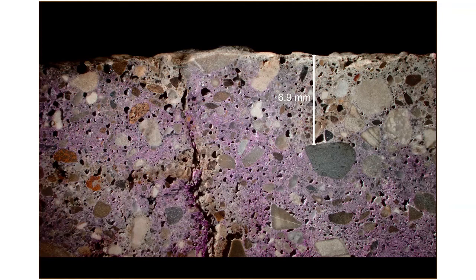Now, another interesting thing to note here, we were talking about air entrainment and the necessity of having little bubbles well spaced throughout concrete to relieve the pressures of freeze thaw and make concrete durable in the severe freeze thaw environments of which we know our bridge decks, curb and gutter, sidewalks, pavements go through. And note all the little kind of black bubbles. We've cast a low angle light across these, so these bubbles show as dark voids. And we see a lot of little voids throughout this concrete.